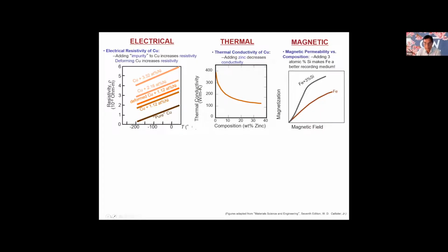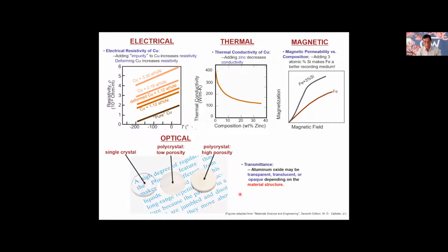Then here you have the magnetic field, and this is the iron. When you add some silicon, you can see the changes in the magnetic field. If you look at some of the optical properties, these are all aluminum oxide, but it has become transparent, translucent, and opaque, and it depends on the material structure. So if you change the material structure, you can go from transparent to translucent and opaque.